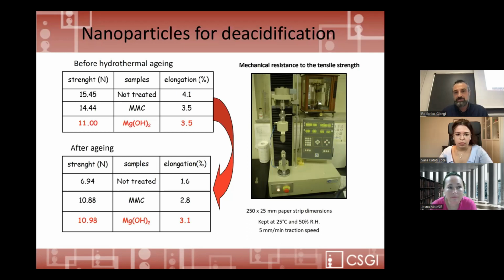We prefer calcium hydroxide for several reasons. But why did we also investigate magnesium hydroxide? Because the intermediate in almost all the deacidification methods available today at industrial level, I mentioned some, I may have the Battelle method and whatever, uses magnesium hydroxide. And so we just wanted to see if the direct application of magnesium hydroxide provides similar results. And this is obviously the case, because the chemistry is very, very simple, nothing different.